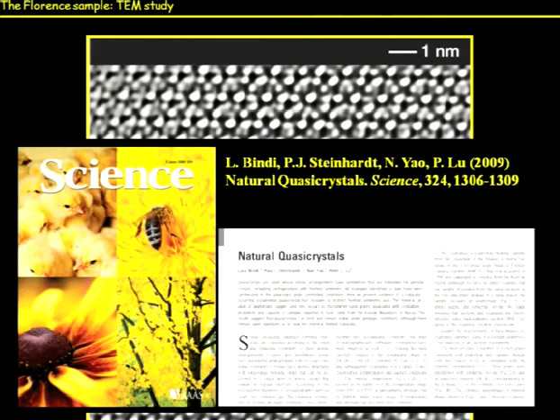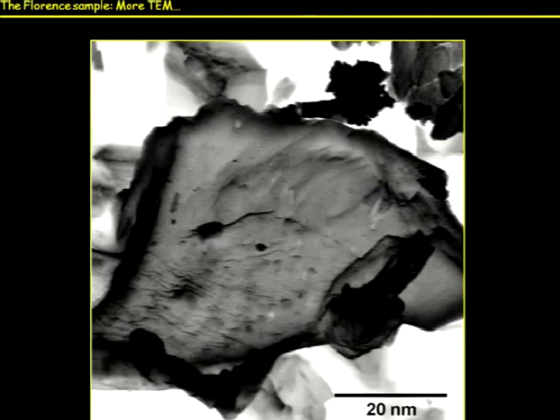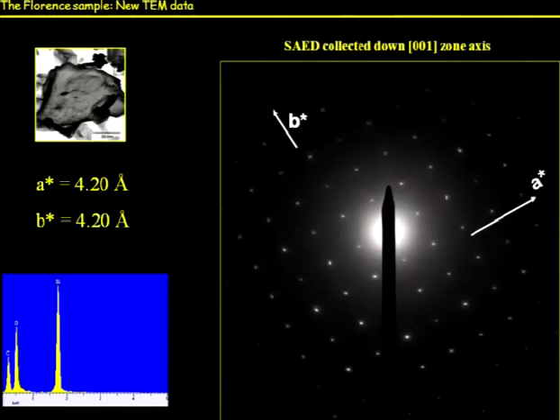How to do this? We have only 3 millimeters of sample. Actually, probably in this period, it came down to 2 millimeters. Well, so the answer was this. The answer to help us with the naturalness problem was this grain, recovered at the same time on the copper grid, which Nan analyzed in Princeton. It is a 50 nanometer size grain, this one. This grain shows only silicon and oxygen, and this kind of electron diffraction.